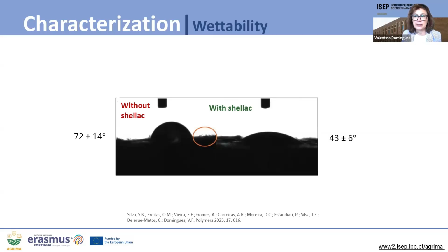A possible explanation for this outcome is the effect of shellac on fiber orientation. As you can see, fibers stand more upright without shellac, creating a textured surface that may repel water more effectively. Fibers align more flatly with shellac, resulting in a smoother surface that reduces water repellence. Despite these findings, both composite surfaces are classified as hydrophilic.